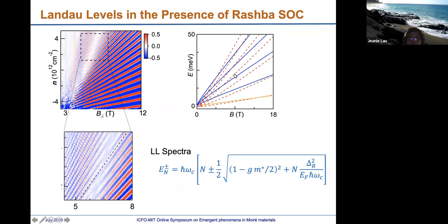And we can see that now we have a series of Landau level crossings, and that corresponds to this node. What we can also understand is why we see this even to odd resolved transition, which is because of the Landau level broadening. When we cross the Landau level, for example, here maybe we are resolved even, and when the two bands, spin up and spin down bands, cross, then the Landau level crossing can produce this even to odd integer state transition.